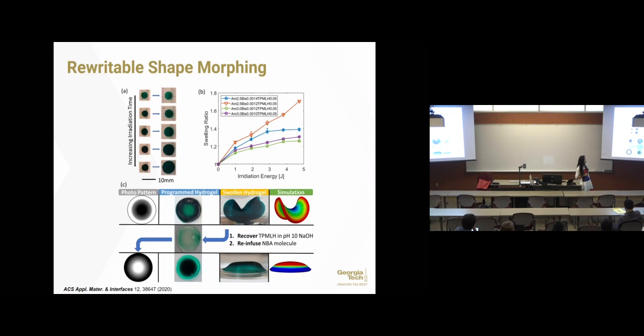And because we are using light, we can apply different light intensities, so we can generate a gradient of different swelling ratios. With that, we can use different photo patterns to program more complex shapes of the gel. For example, this is a photo mask that allows more light to penetrate through the outer region and less in the middle. This is how the gel looks after activation. After we put it in water, it becomes a shallow dome shape because it swells more in the outer region. And we can accurately capture or predict this behavior using our model.